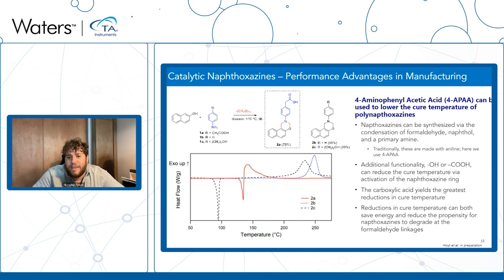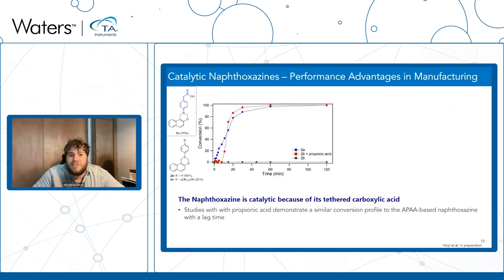But one of the things that Caroline did first is we said, hey, we have these two materials. On the bottom here, you see our naphthoxazine-based resin. On the top here, you see our bio-derived naphthoxazine resin with its catalytic moiety. What Caroline did on the DSC once again, studied the conversion as a function of time at a temperature of 150°C. And she showed that when you have your bio-derived resin, you slowly can get complete conversion of your material in under 2 hours.